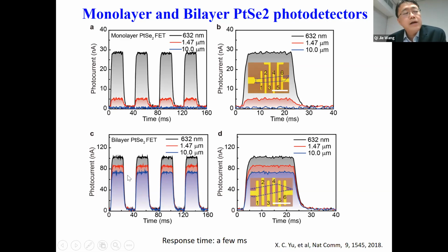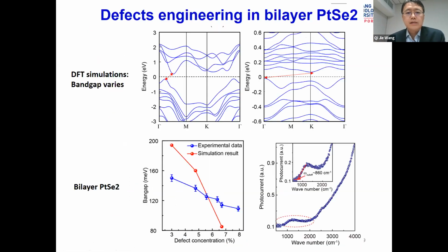However, one interesting point here is that based on the calculation, bilayer PtSe2 should have a bandgap of 0.3 eV. So by right, this material should not show any photo response at 10 micron, because 10 micron is close to 0.1 eV. Based on that, we further investigated the defect contribution to the bandgap.